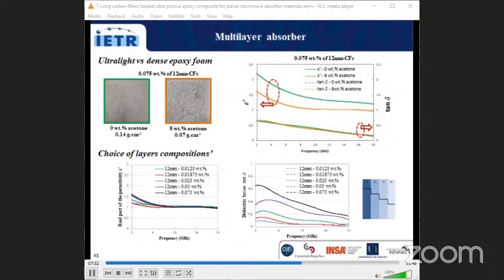Here I present also the dielectric properties of 5 samples loaded with different concentrations of carbon fibers from 0.0125% to 0.075% of carbon fiber. We observe that the permittivities of the samples are very close to the permittivity of air, which increases the impedance matching between the air and the absorber.